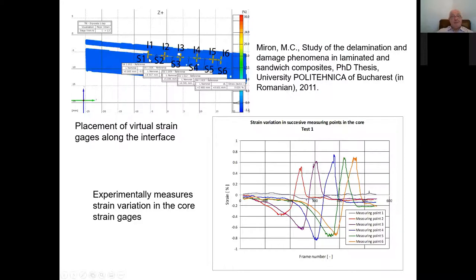What we did, we emulated, let's say, virtual strain gauges, which were in different positions across the delamination in between the, let's say, core and the skin. Measuring, of course, the strain variation along all these virtual strain gauges as the crack was propagating, then here you have the successive variation of the strains in different points measured along the interface.